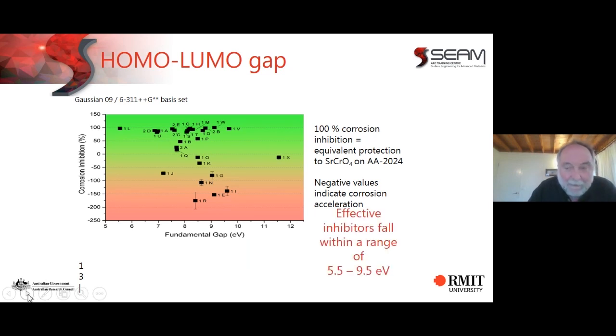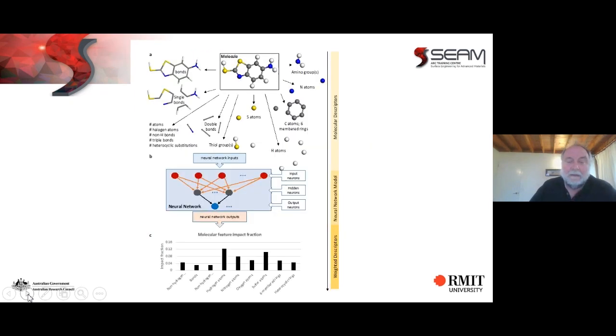So we then just say, well, maybe we can incorporate more different parts of the molecular structure into our models. Now, again, I need to step back and explain one thing. In connecting the models together, and in particular in connecting molecular models and electrochemical models, at the moment we do not have a rigorous process-based model that can do that. So we need to use statistical or neural network or machine learning approaches, if you like, to connect that. And so what we do is we put in the molecular features on one side of our model, and we put in the electrochemical properties on the other, and try to construct a neural network between them all.